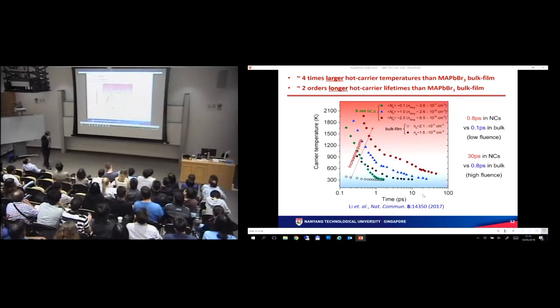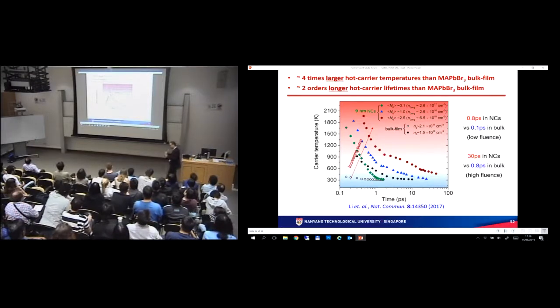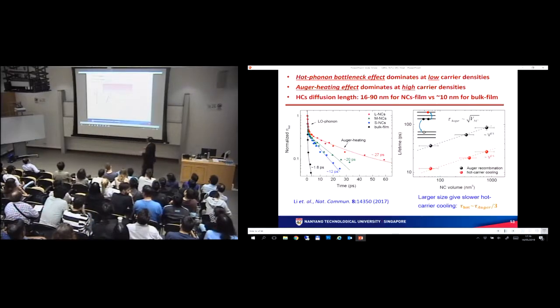What we found from this is, as you go to nanostructure, you get about 4 times hotter carrier temperatures, and your hot carrier lifetimes can increase by almost 2 orders of magnitude. Now, this is a very significant lengthening, because with this kind of lengthening, you can get thicker layers and you can make a practical device out of it. So that is the basic understanding behind this.